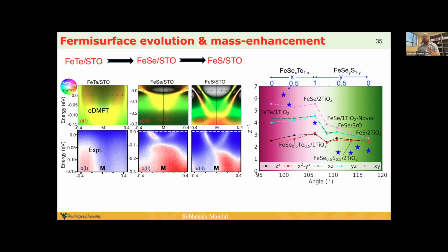I think we need better resolution of ARPES for all these films, which we wait to see, and then we can identify the orbitals and get the mass orbital by orbital. So these are Fermi velocities of the electron pockets, from curve fitting of this pocket and getting the curvature. That's not exactly matching the calculation, because it's averaging it out, but more or less the trend is captured.